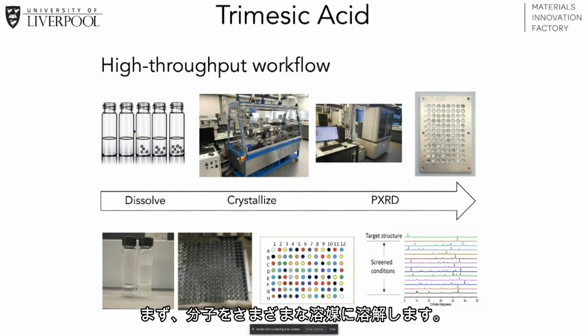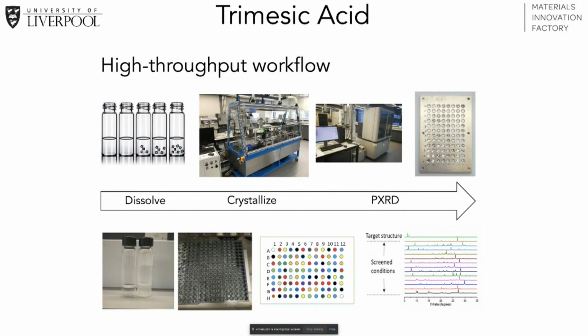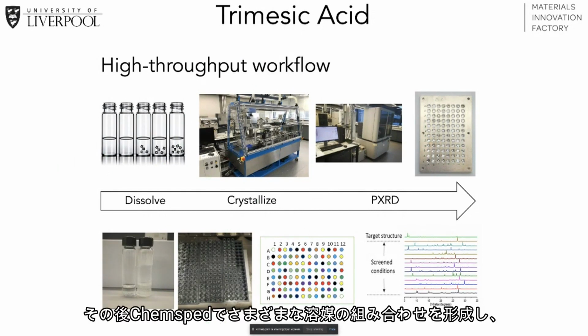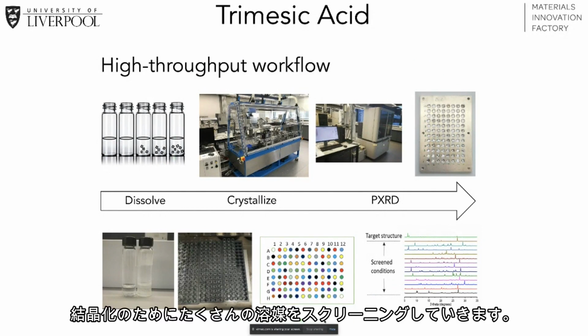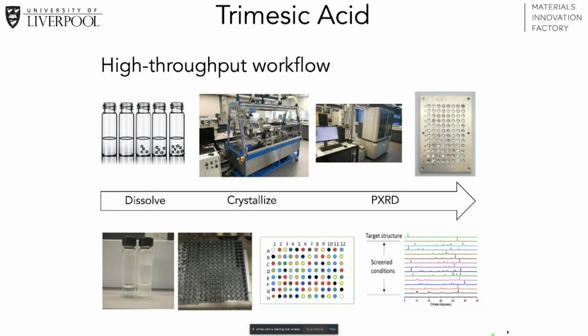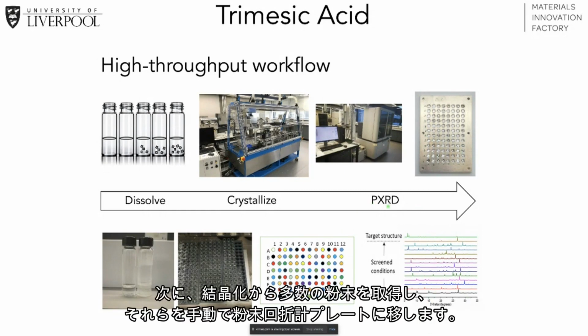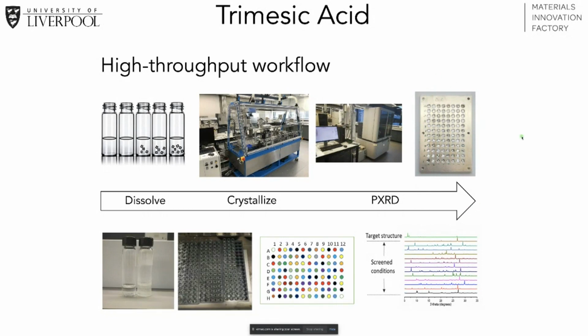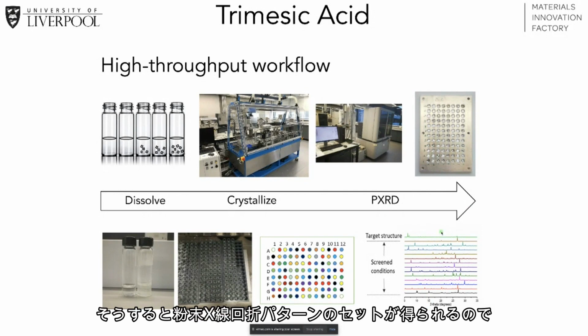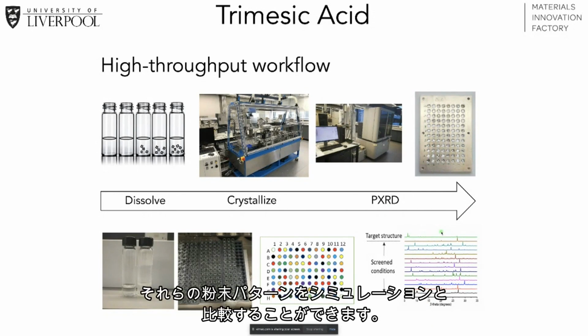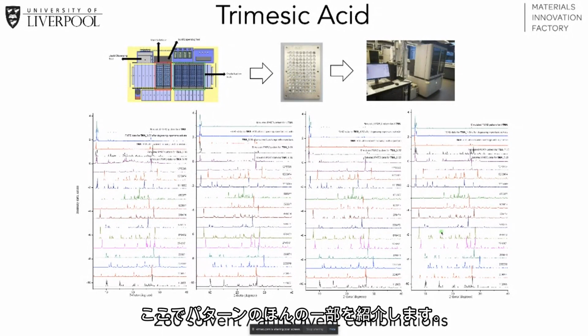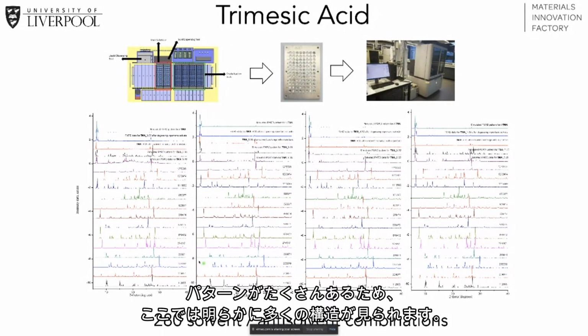And basically, we dissolve the molecules in various solvents. The Chemspeed then forms different solvent combinations, and we can screen a very large number of solvents for crystallization. Then we get a large number of powders from the crystallization. We transfer those, at the moment manually, into a powder diffractometer plate, and then you get a set of powder X-ray diffraction patterns. And you can compare those powder patterns with the predicted patterns from the simulations. Here are just a few of the patterns. You can see, obviously, we're getting lots of different structures here because there are lots of different patterns.